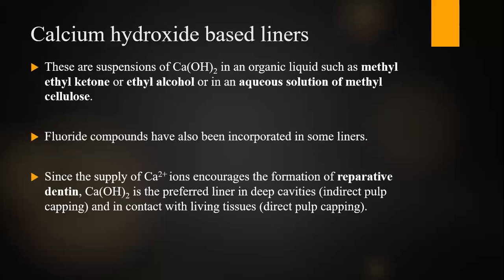Then calcium hydroxide based liners. These are suspensions of calcium hydroxide in an organic liquid such as methyl ethyl ketone or ethyl alcohol, or in an aqueous solution of methyl cellulose. Fluoride compounds have also been incorporated in some liners. Since the supply of calcium ions encourages the formation of reparative dentin, calcium hydroxide is the preferred liner in deep cavities, for indirect pulp capping and in contact with living tissues in case of direct pulp capping.